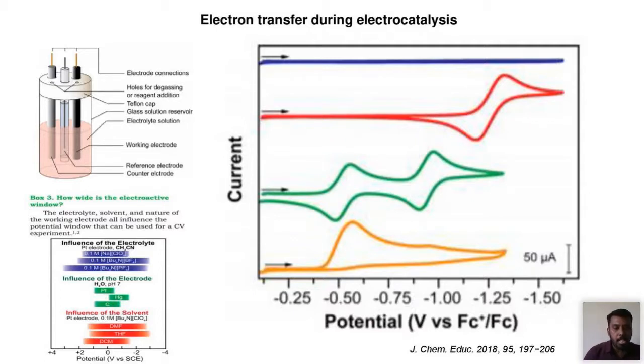For example, in the case of sodium perchlorate, the potential window will be 2 volts, whereas if you use some ionic liquids, you can extend the potential window to 3 volts. So based on the electrolyte, you can tune the working potential window. In the case of batteries, we always need a broad, wide working potential window. In the case of electrocatalysis or some nanosensor, you need only a minimum potential window, like within 1 volt you can do that process. For example, for water splitting, you need a much higher potential window like 1.23 or 1.3 volts, because the thermodynamic potential for splitting water into hydrogen and oxygen is 1.23 volts. So you need to supply some energy higher than that. So we have to focus on things like the type of electrolyte, electrolyte species, and pH for determining the working potential window.